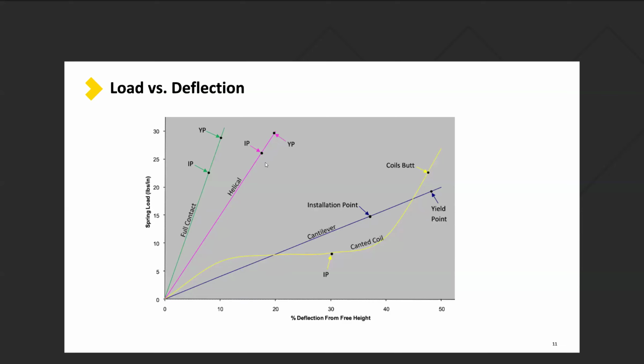And these charts can all be found on our website for the individual springs and their specific load versus deflection curves. The interesting one here is that canted coil. You'll see that it has a nice flat section here where the load doesn't change with the deflection. That's pretty unique in that you can load this thing anywhere along this section and have the same force. So if you have a very friction sensitive application, or you have an application for long life in your sealing, high-speed rotary applications quite a bit use canted coil for that reason, that you have just a nice flat curve and a constant force over the usable life of the seal. So as the seal jacket wears, your force stays the same. Whereas if you look at a helical spring, as that seal jacket wears, your force falls off very, very quickly, which is why we would not recommend helical for any kind of dynamic service.